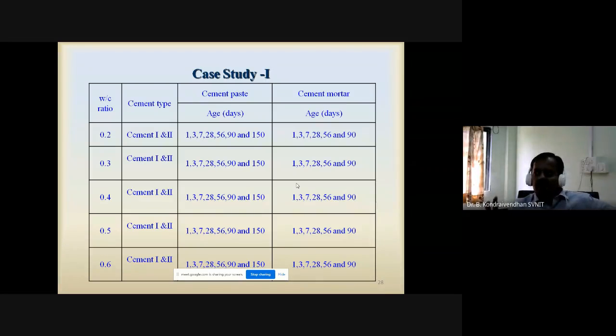Okay, so how to determine the pore size distribution parameters for the cement paste? For that, we have taken different water cement ratios: some low, some high, and some intermediate. For example, 0.2 and 0.3 are the low water cement ratios, 0.5 and 0.6 are the high water cement ratios, and 0.4 is the intermediate water cement ratio. We have also taken two different types of cement, one coarser cement and another finer cement.